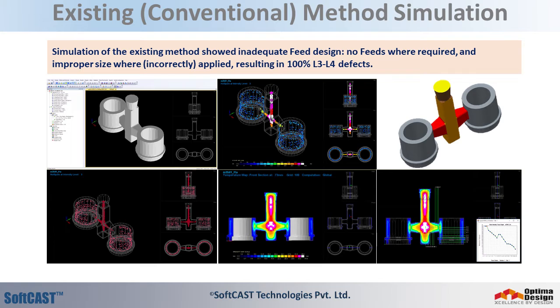The foundry was experiencing defects with their existing method. Simulation of the method showed inadequate feed design. Feeds were not applied at the locations required. And at the incorrect locations where they were applied, they were incorrectly sized. All this resulted in 100% level 3 and level 4 defects.